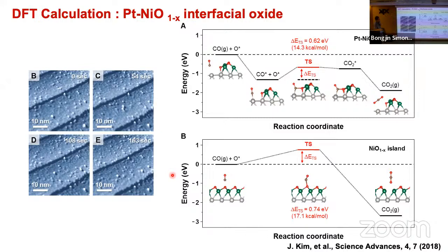And when we calculated just forming nickel oxide versus forming the platinum nickel interfacial oxide, and compared these two, the reaction energy is much lower in the latter case. So the platinum nickel interfacial oxide is probably what we are seeing. And at the time, okay, that's one approach. That's how we could interpret our experiment. So we moved on.